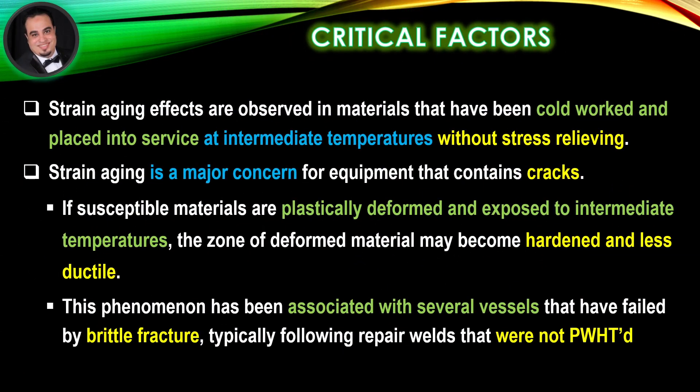Strain aging effects are observed in materials that have been cold worked and placed into service at intermediate temperatures without stress relieving. Strain aging is a major concern for equipment that contains cracks. If susceptible materials are plastically deformed and exposed to intermediate temperatures,